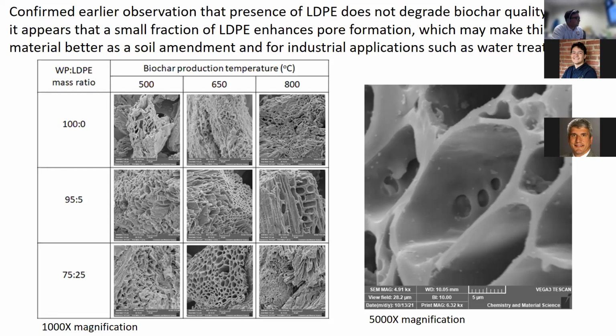And what we found consistently is that higher temperature creates a higher surface area and a higher density of micropores. But this data, in combination with a number of other measurements that Ivan took, indicates that the presence of the low density polyethylene has very little impact on the properties of the biochar. In fact, the presence of the plastic phase actually enhances the formation of micropores in the biochar, which is illustrated in the center of the figure on the right.